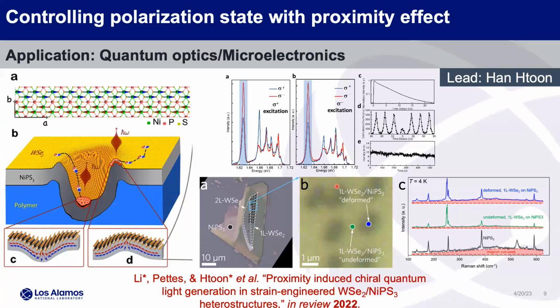And then just to show the characterization that I do, this project is led by Han Htoon, but the characterization that I do is we're looking at the difference between these punches in terms of the vibrational spectra of the NiPS3 on and off of the punch. I personally didn't pick up a lot of strain. There's NiPS3 peaks and then there are peaks from the tungsten selenide. This is a Raman spectra, but I did see a big, measurable difference in the magnon intensity.